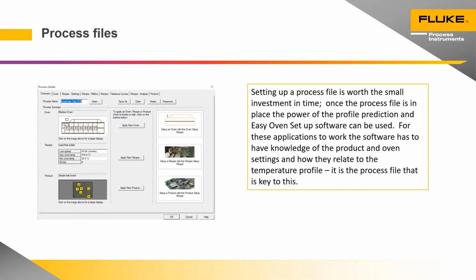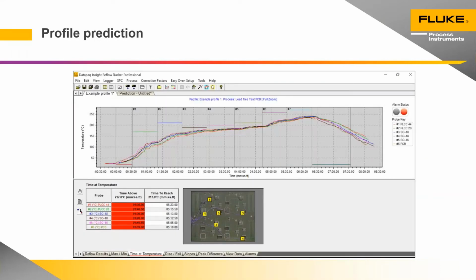And the software uses this distance information contained here to correct those peaks, so that when we look at the profile, all of the temperature peaks are aligned. That's standard practice in reflow soldering. So, having invested the time, created the process files so that every time you download your results, you put a process file on them, you then end up with a screen like this on your software. You have a time and temperature graph, some temperature zones with the settings, a picture of the product, and in this case, you've got an alarm. Everything is red, a time above liquidus, in this case 217 degrees, has been exceeded.